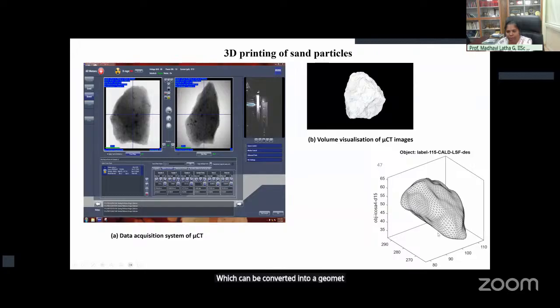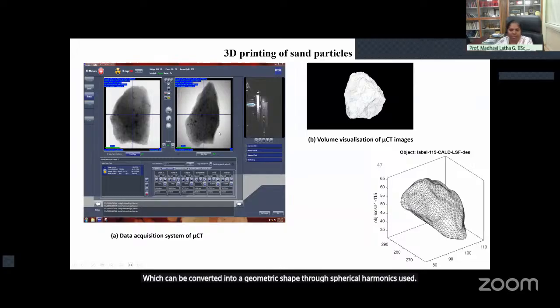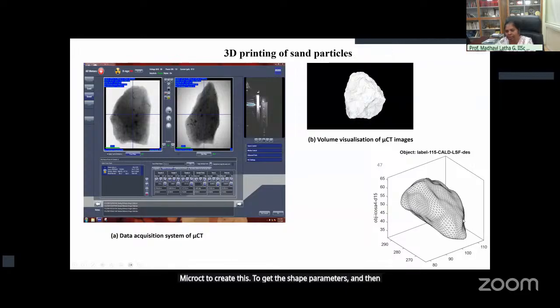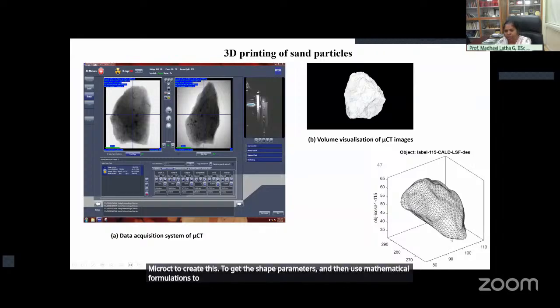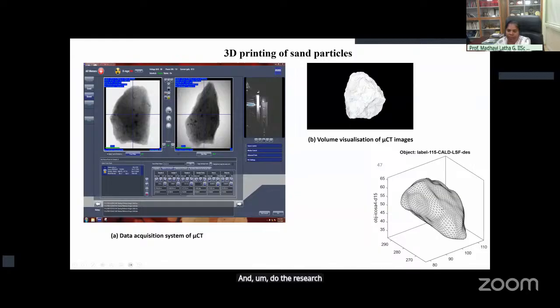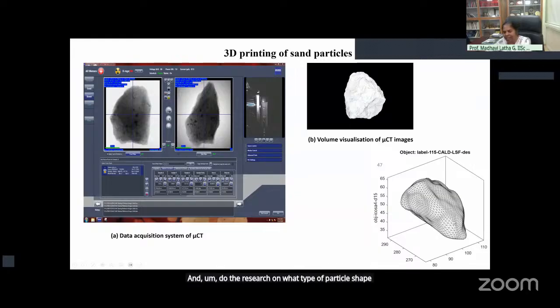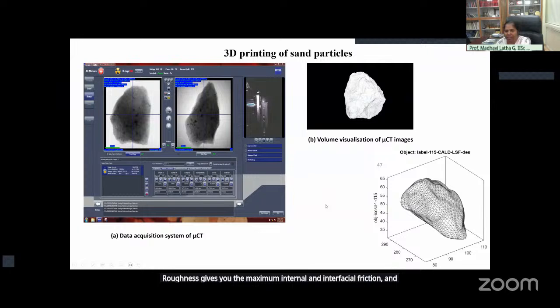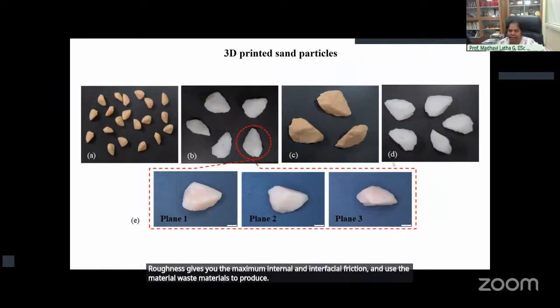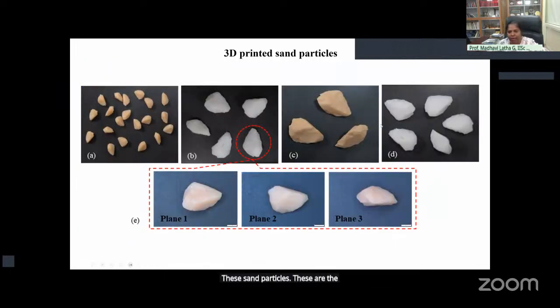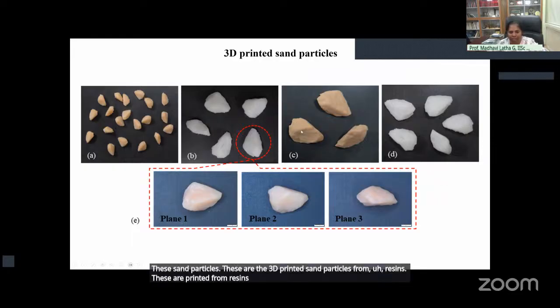So this is the micro CT of a natural sand particle, which can be converted into a geometric shape through spherical harmonics. You use micro CT to get the shape parameters, and then use mathematical formulations to create the geometry of these particles, and do the research on what type of particle shape and size and surface roughness gives you the maximum internal and interfacial friction, and use the waste materials to produce these sand particles. These are the 3D printed sand particles from resins. These are printed from resins using polyjet printing technique.